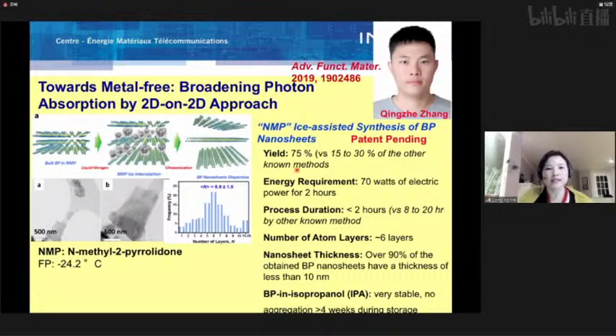The advantage of this method is obvious. For example, we have a much higher yield, 75%, with respect to the normally reported 15 to 30% yield, and the energy requirement is significantly lower, and the duration is also much shorter, less than 2 hours, as compared to the normally reported 8 to 20 hours. From this synthesis, we can get BP nanosheets with about 6 atomic layers. Over 90% of BP nanosheets have thickness less than 10 nanometers, and also they are colloidally very stable. No aggregation was observed over 4 weeks during storage.